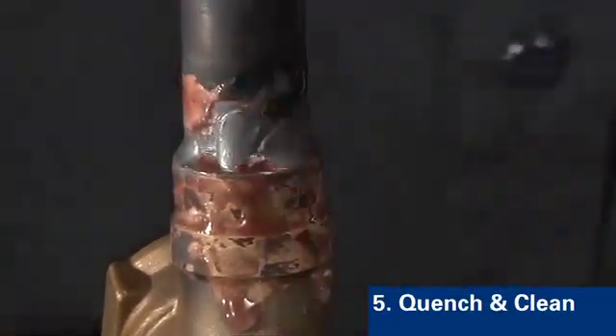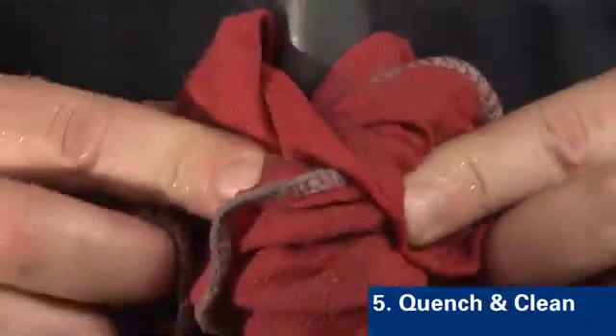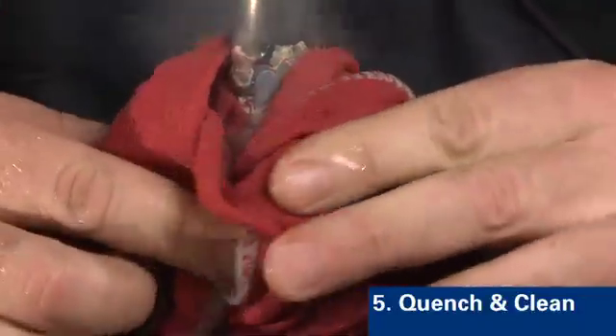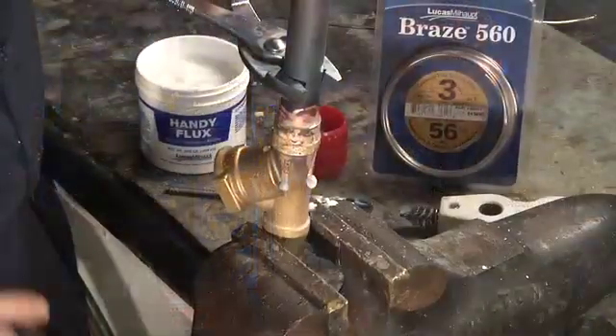Step 5 is to quench the part. This will shock off the majority of the flux residue. Wait until the filler metal has cooled below its solidification point before quenching. Make sure all color has left the assembly prior to quenching. This will ensure that the filler metal stays in the joint.